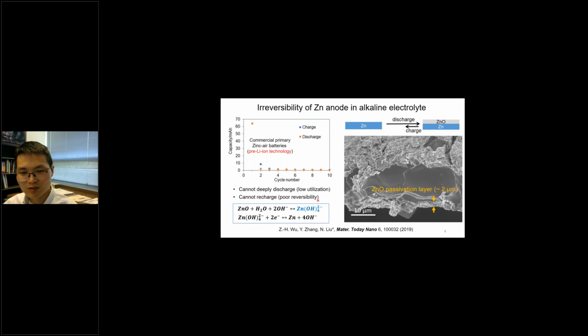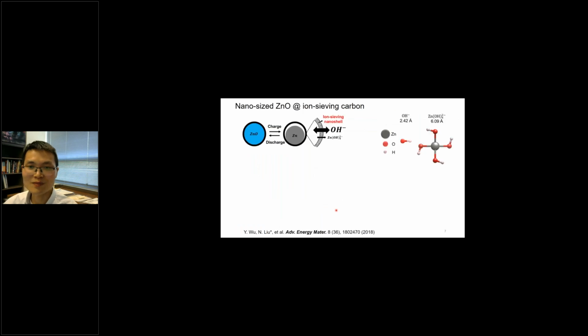Another problem is that during the conversion of zinc oxide to zinc metal, it goes through a soluble species called a zincate ion. This ion is soluble, so it can dissolve in the electrolyte and move everywhere in the battery. Then you will have a shape change and also uneven deposition of zinc in your battery. So the active material is moving all the time, and that is the second problem.